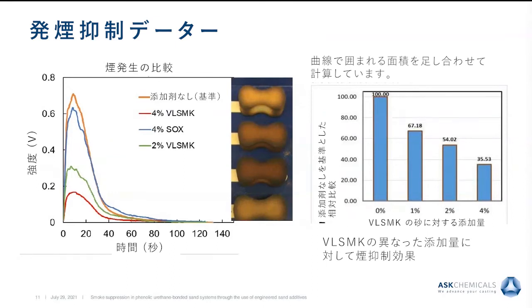As you can see clearly here, as I explained earlier, if you have a plot of intensity as a function of time, and you take the area under the curve, that will be your total smoke. If you see here, the green and red curve definitely shows some reduction. To quantify this a little bit easier, you can sum these individual points, get the area under the curve, the total amount, and divide by the intensity as a function of time summed in the presence of no additives. When you do the normalization, you can see at 0% you had 100% total smoke. As you increase the amount of VLSMK additive, there is a decrease in the total smoke. To determine the smoke suppression, you do 100% minus this number. That will give you your smoke suppression.